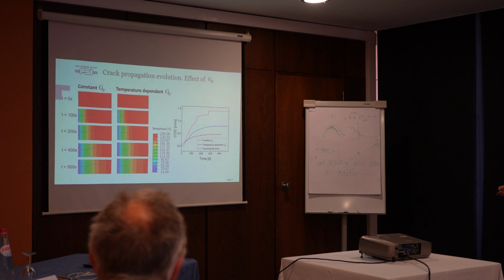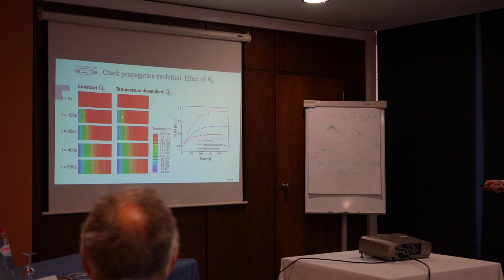So the next step that we did, or the next analysis that we performed, was to change the energy release rate, and we make it dependent on temperature. And here you see the contours of the temperature and the crack propagation. So here already at 100 seconds, you see that the crack is already at the very hot part of the cylinder. Here the crack propagation is controlled by the temperature profile.